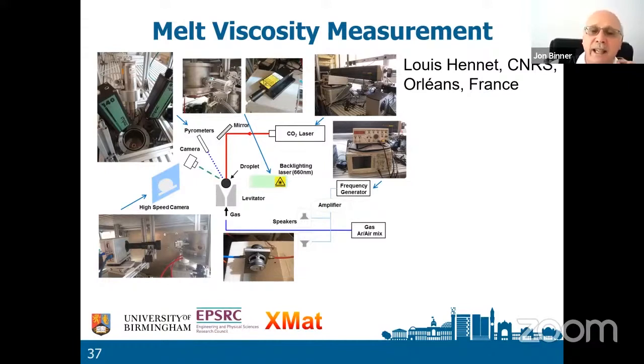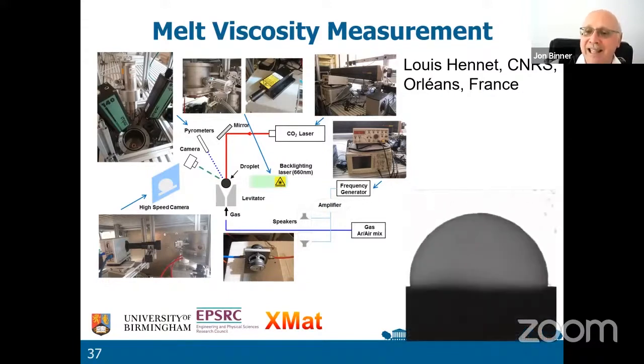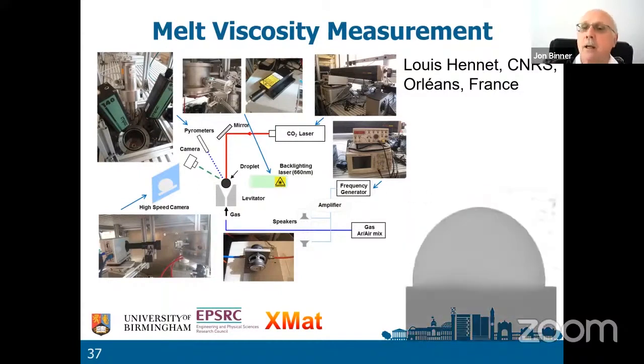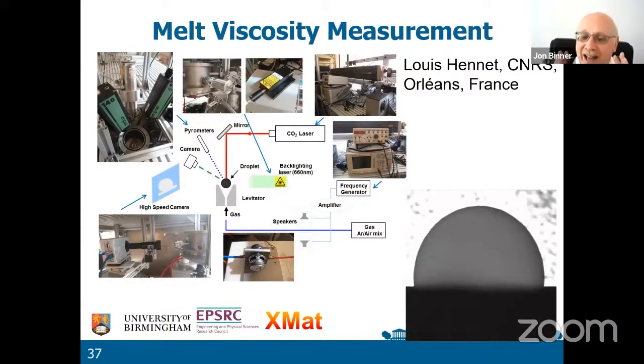And what he does is he blasts some sound at the droplet, causing the droplet, which is levitated, to vibrate. And this is the vibrating droplet. There is a droplet of molten hafnia at 3000 degrees centigrade, and then it vibrates, and then the vibration stops. If we just see that again, you can see the droplet vibrates, and then the damping in the system causes it to stop. And by monitoring that damping, he can get the values that he needs.